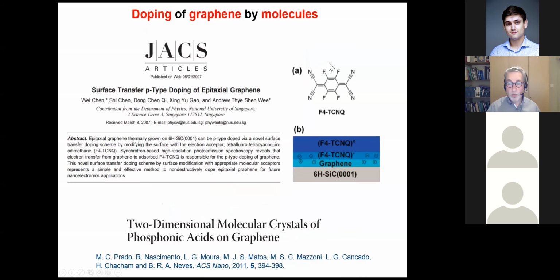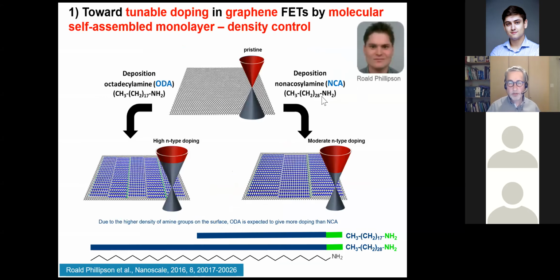And we were absolutely not the first to do so. Quite some years ago, a group illustrated that if you bring these molecules in contact with the graphene substrate, you can dope graphene. But we thought a bit differently. We thought differently in the sense that in order to have the best possible control, you need to have control of the density of the doping groups in contact with the graphene substrate.